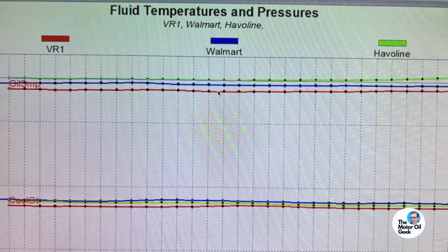And really what you see is that the oil that is the mineral base, the Havoline, has the highest temperature, and then the 2 synthetics are slightly lower. That jives with what we've seen historically doing oil testing: mineral oils have a lower specific heat value, therefore they tend to run hotter under the same conditions. They just can't move the heat as well. Synthetics move the heat better, therefore they run cooler, which is why we use synthetics in the race cars, because they cool better, not just make more horsepower.